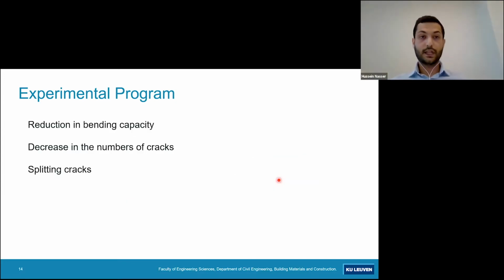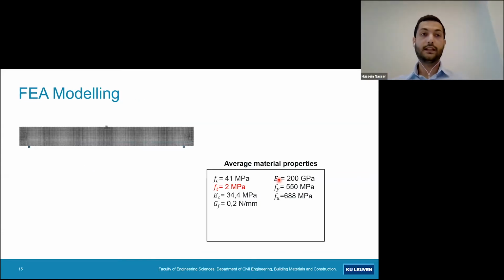Therefore, corrosion causes reduction in the bending capacity due to the formation of pits and the loss of cross-section of the steel. It also, due to bond deterioration, can cause a decrease in the number of cracks and the formation of splitting cracks. Both types of damage are necessary to be taken into account in a model. After discussing the experimental program, now I'm going to move to the numerical modeling, which will be validated on the load deflection curves and the DIC results of the cracking patterns.